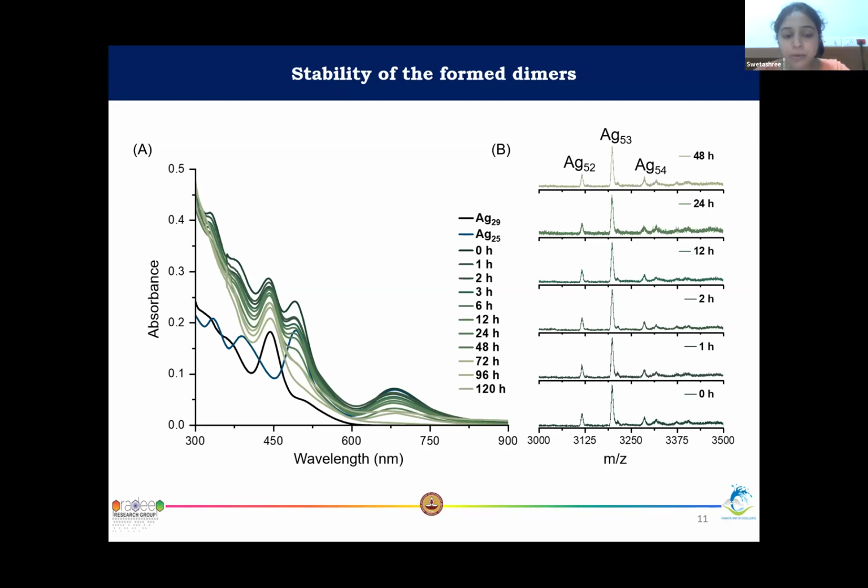My question in that. Actually, what we have shown here is these dimers are stable species. When we are mixing the two clusters, the dimers are coexisting with both of the parent nanoclusters in solution. Till the time one of the nanoclusters is present in the solution, this dimer will also be stable in the solution. Once the parent nanocluster is degrading, then we are not observing the dimer also. But we have to think about how we can increase the stability of the dimers.